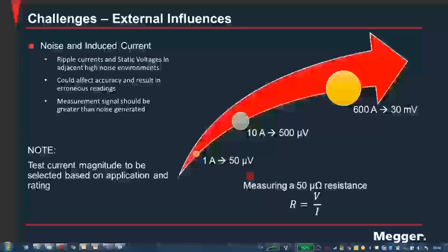This is one of the reasons why we need to use higher current sometimes, because we need to get a higher voltage drop to make the voltage measurement higher than background noise. You also can test with 600A to get more voltage drop. But please keep in mind, even though we can increase the test current, we need to be careful because we still need to follow the standard. The test current should not exceed the rating of the test specimen. So you can inject current as high as possible, but it should still be less than the rating of the test specimen. This is very important to remember.